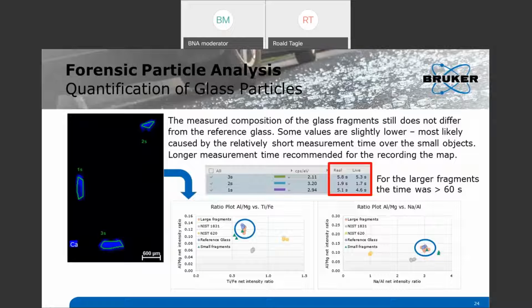So you should consider, when you do an area scan as opposed to a point analysis, that you accumulate for the amount of time that you previously defined as required for this kind of work. So basically, point analysis is one option. Scanning is the one that we would recommend, as we have the possibility to identify non-homogeneous samples.